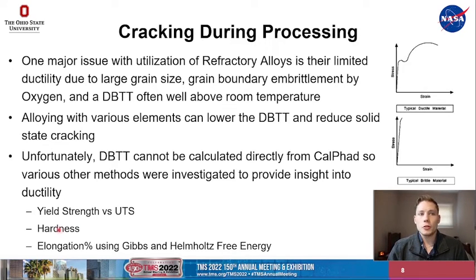Unfortunately, the ductile brittle transition temperature cannot be calculated directly from CalPhaD, so a few other methods were investigated to provide insight into ductility. These were yield strength versus ultimate tensile strength, hardness, and elongation percent using Gibbs and Helmholtz free energy. The yield strength and hardness were two factors that we hoped to get out of CalPhaD, and the elongation percent we calculated using various equations that we found in literature.